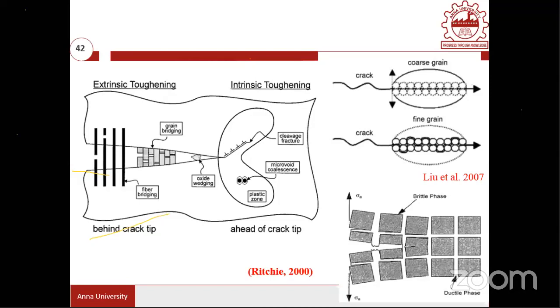The extrinsic mechanism is by creating more boundaries. That means you are deflecting the crack. As a result, you are creating new surfaces. So the energy will be spent for creating the new surfaces, and also the driving force will be reduced because of this. And also when you have a larger amount of barriers like particles, new surfaces will also be created. So that is crack bending.